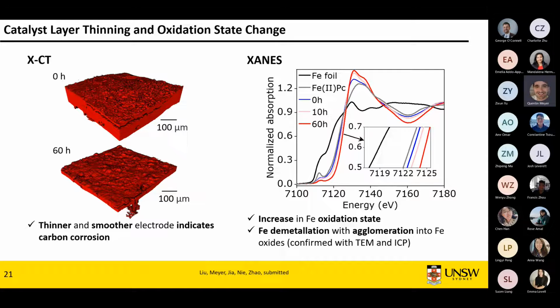Now, we also did some XANES measurement. So we took our entire MEA and we ran different MEAs that had operated for different times. We ran them, sealed them, then went to the beamline the next day and tried to characterize them. What we can clearly see is we're confident we've got single atom catalyst. So that's a good step. Now looking at our iron edge, you can see shifting towards higher and higher oxidation states. We coupled that with more techniques such as TEM and ICP. TEM shows that we have some small iron oxide nanoparticles on the catalyst surface. ICP shows that we are losing a large amount of our iron.